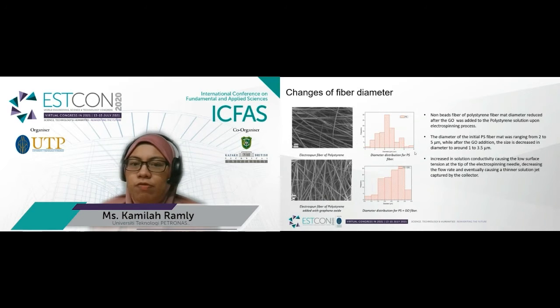The diameter of the initial polystyrene fiber mat ranged from 2 to 5 micrometers, while after the graphene oxide addition, the diameter decreased to around 1 to 3.5 micrometers. This morphology was most likely affected by the increase in solution conductivity, causing low surface tension at the tip of the electrospinning needle, eventually causing a thinner solution jet to be captured by the collector.